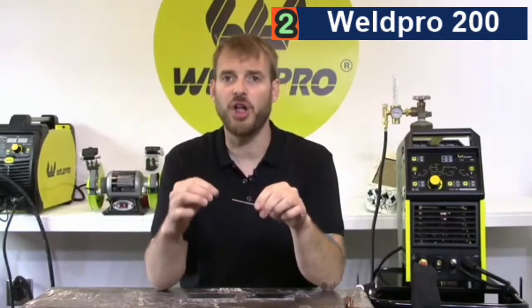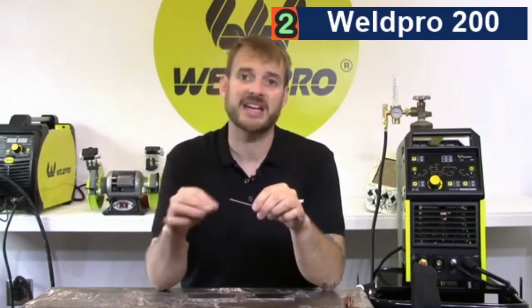When grinding tungsten, it's important to get a nice symmetrical cone. We're going to put our tungsten against a grinding wheel and we're going to twist it. One very important thing to note, don't grind the taper on your tungsten more than 1.5 times the diameter of the tungsten. If you have a very long point, under high current conditions, the tip of the tungsten can fall off due to erosion and land in your weld pool, causing contamination.